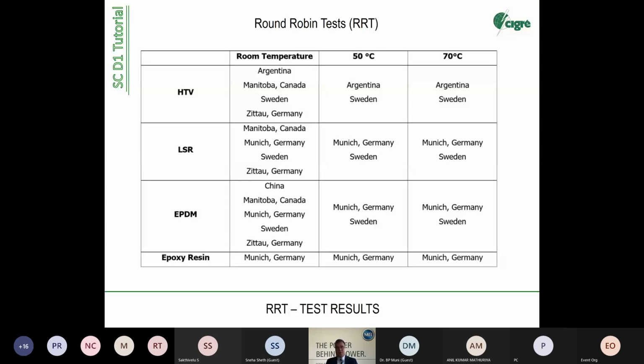What you also see here: not everybody tested the same materials, but most tested the HTV rubber. It's a commercial grade silicon rubber used mainly in composite insulators and cable terminations. Liquid silicon rubber has the same application range, going also deep into the cable systems. EPDM is from cables and also from former insulators that used this as housing material. Epoxy resins are a wide group of materials applied in medium and high voltage equipment, maybe in internal insulation. Most of these epoxy resins are filled with a mineral filler, quartz powder, in order to set up the desired conditions. So this was the round-robin test.